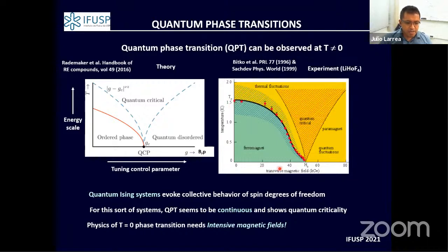With the application of a magnetic field, you change the correlations. What you're doing is following a thermal line where basically all the physics is explained by classical Landau-Ginzburg theory. But as you decrease the Curie temperature, you suppress the transition continuously, and this continuous suppression defines the quantum critical point.